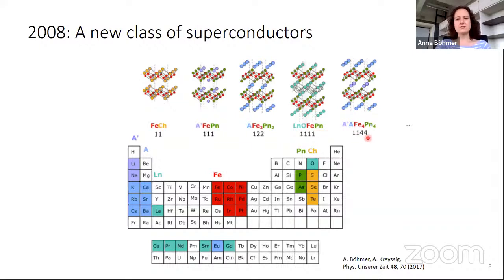And one thing that's really fascinating about them is we have a lot of them. We have different materials. There's some abbreviations here. They come in different chemical structures. What they have in common is iron, in red here, and then typically arsenic, sometimes phosphorus around them in layers. But we can use many other elements as well. So there's a good part of the periodic table that can be taken, built according to these structures, and every time we find a superconductor. That's quite amazing. So there's a lot of tuning parameters, even a lot of chemical tuning parameters we can play with.